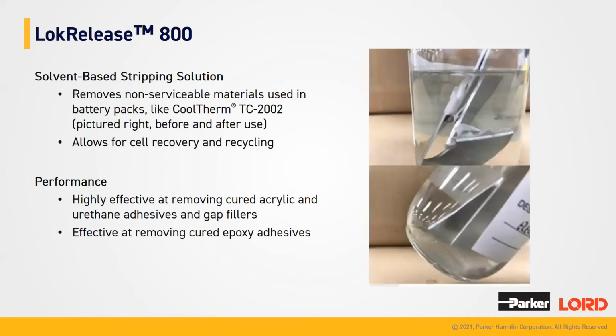Introducing LokRelease 800. This is a material that we qualify as a stripping solution. The idea here is you have a solvent-based material that is meant to remove cured, typically non-serviceable materials from their substrates. The pictures on the right are actually small coupons that are bonded together with TC2002. As you can see here, they're soaked in this vial, and then after a certain amount of time, the adhesive actually dissolves, allowing for the metal substrates to be separated.